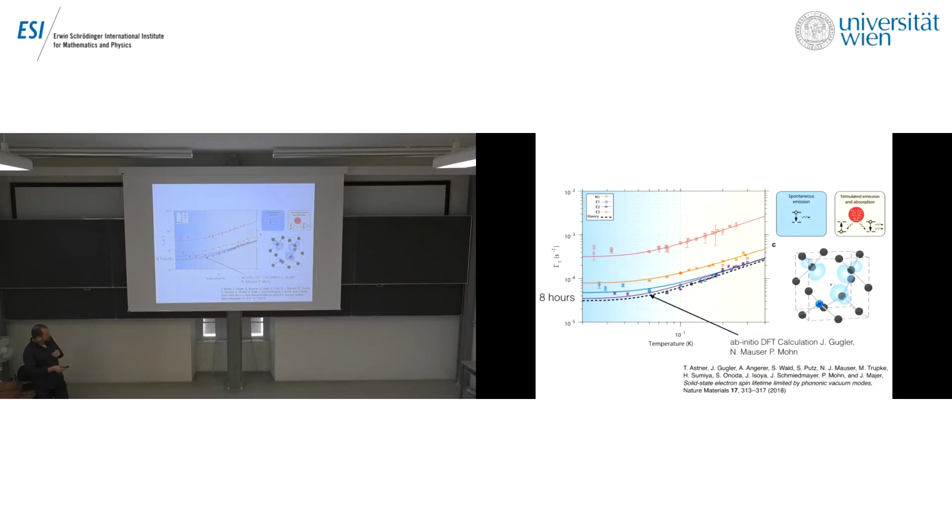So this is really the first measurement of the spin lifetime of NV centers below temperatures where this is in transition frequencies. So this is about here, 145 millikelvin. So we're below that, and it's really 8 hours. So it's a super long T1 time for the system.